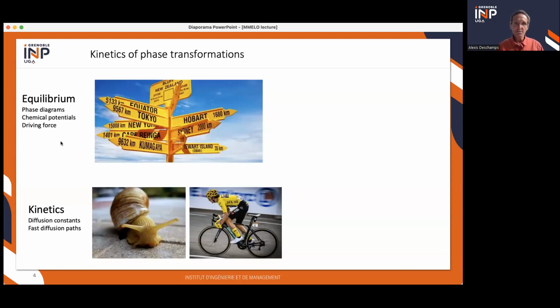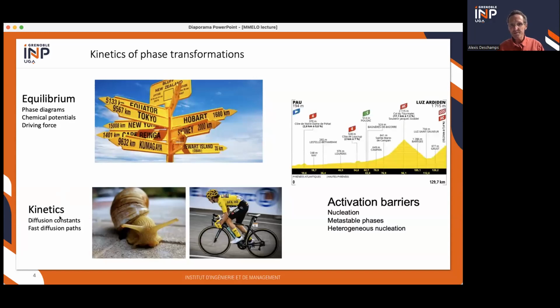And so knowing the kinetics of the phase transformation will involve at least these two things, and many others, among which one important point is the presence of activation barriers that can make phase transformations impossible, and that will increase by huge amounts the diversity of phase transformations that you will actually see, just because you want to avoid some of these activation barriers and you try to find some other trajectories to equilibrium.